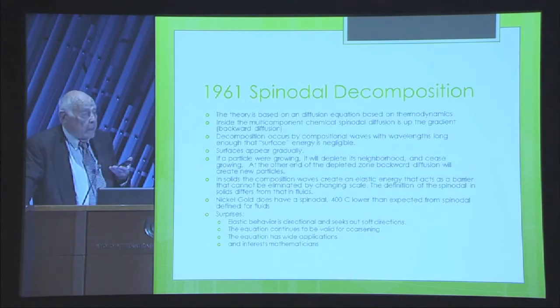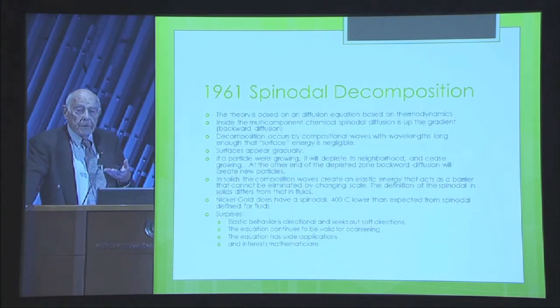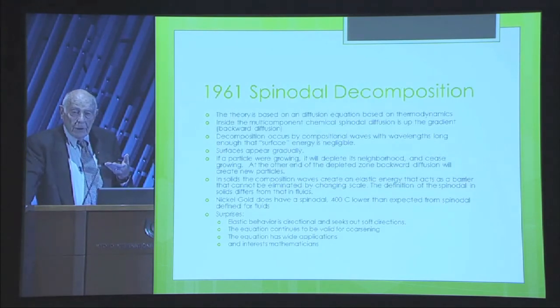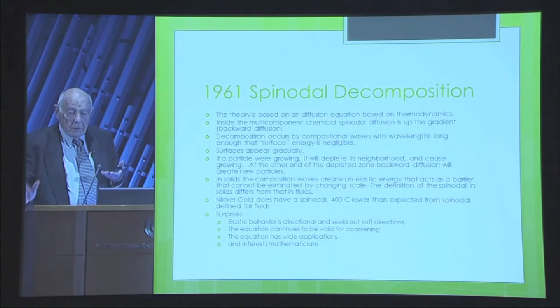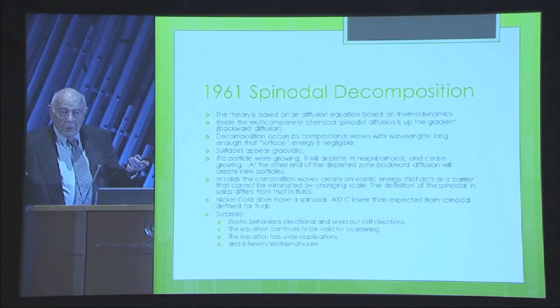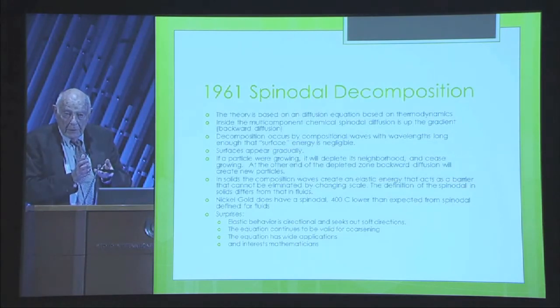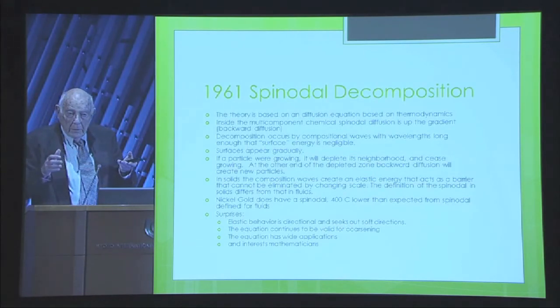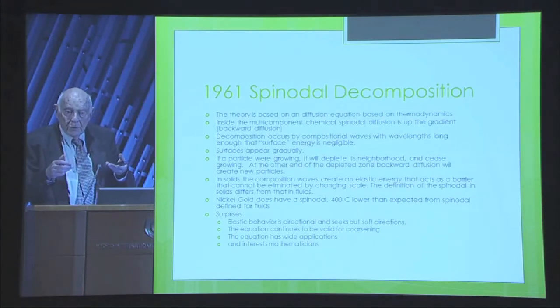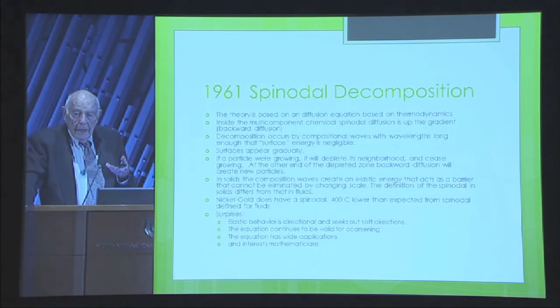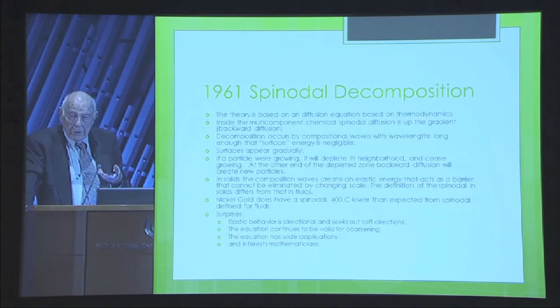What I didn't know at the time was that mathematicians had done a lot of work with the equations of diffusion, and they had found that it was ill-posed, it had no solutions. You could not tell after the ink has spread through the water where it had come from. You can't run it backwards. And running diffusion backwards in time is exactly the same as running normal diffusion back in time to try to predict what happened before. I had added a term to this diffusion equation which regularized it, which meant that the mathematicians suddenly had a toy with which to play.